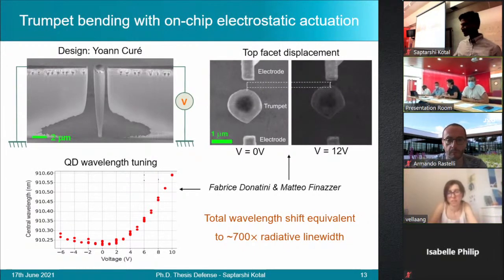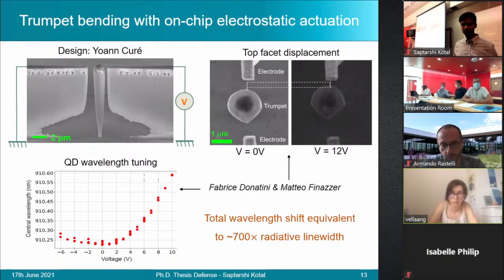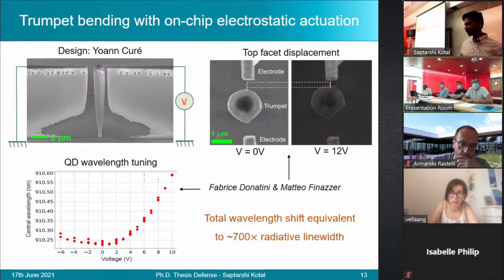A reason why we might be observing a bigger shift in the SEM images than we were expecting is that we are observing with an electron beam. In the process, we are depositing some charges on the device, which might make it more polarized. And as you rightly pointed out, the measurements of the spectral shift were done with the SEM turned off. So we were just measuring the photoluminescence and looking at the wavelengths there. When we are doing the wavelength shifts, it seems to correspond more with the simulation. So it's probably an influence of the SEM.